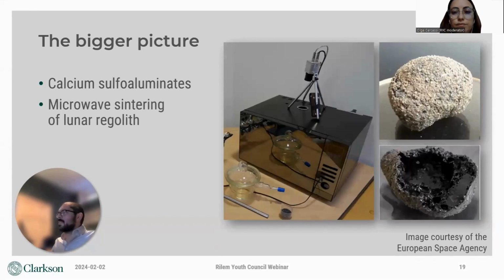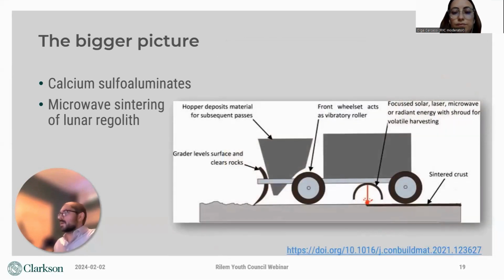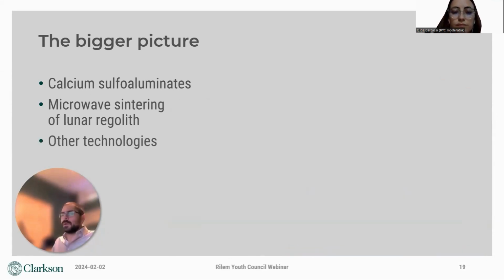There's also microwave sintering of the lunar regolith, where the regolith itself is melted and fused together to form a solid matrix. This is probably the most mature technology, and a great deal of thought has been put into how it can be used to make landing pads on the lunar surface. Here's one iteration where a lunar rover could theoretically be used to autonomously grade, compact, and sinter the regolith, forming a landing pad. There are also a series of other technologies that are quite promising.